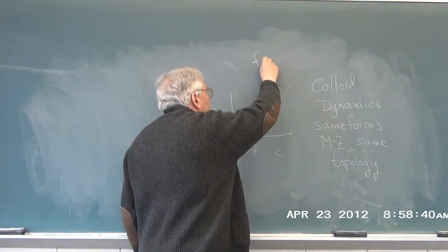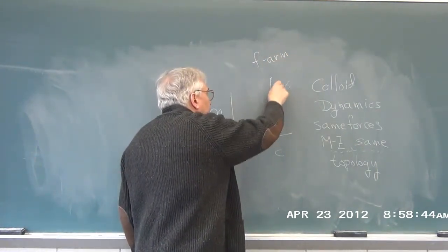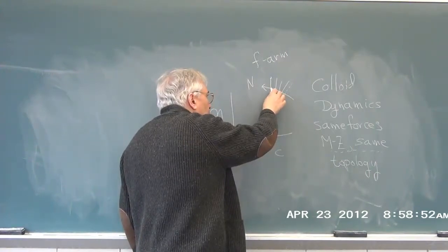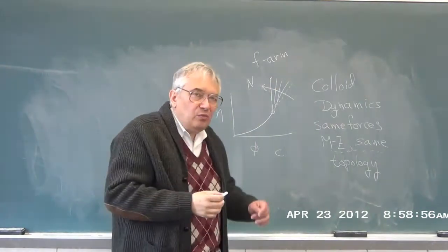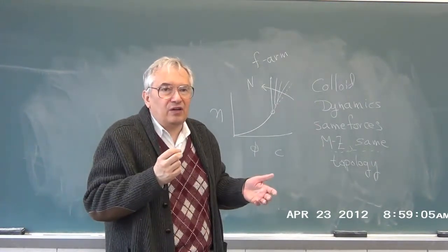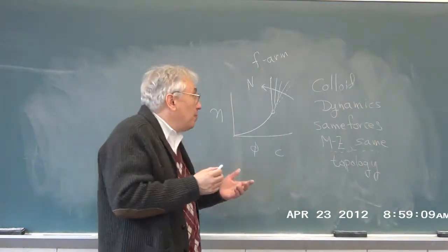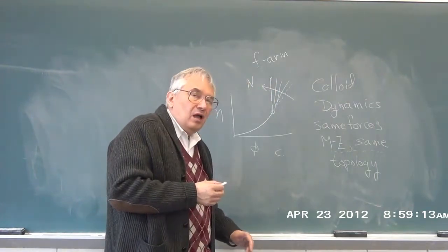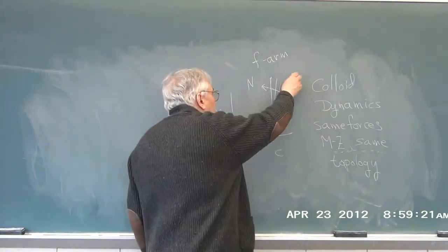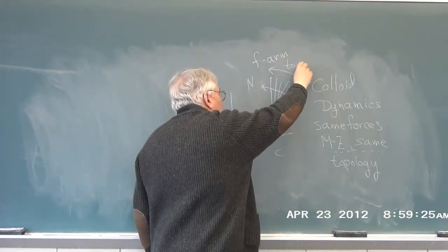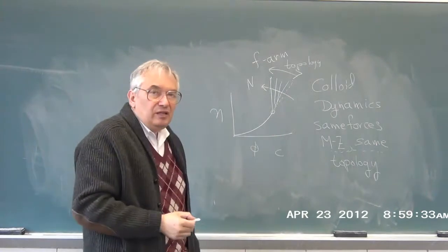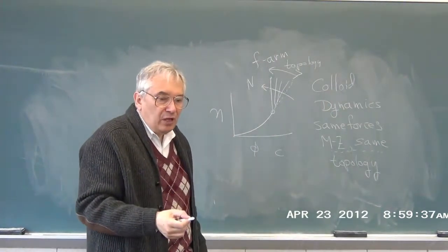If, however, you look at many-armed stars, the stars start out down here, and as you increase the number of arms, you get all the way up to here. That is, as you look at things that look less and less like a single random coil, and more like spheres, like 200-armed stars, which are fairly spherical, you find there's a transition from polymer behavior to spherical behavior, and therefore this piece could be assigned to topology. However, the fact that you see a power law at all is clearly not due to topology, because you see it both for spheres and for polymer chains.